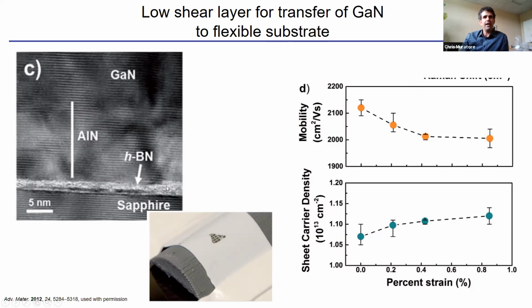And boron nitride has a super low shear strength. It's very easy to tear it apart, just like it has a structure that's a lot like this mica. It's really easy for me to tear a sheet off of the mica, and it's really easy to break this hexagonal boron nitride layer, which is like 3 or 4 or 5 layers. It's easy to split it in two. And so you can grow this GaN device and then tear the material off and attach it to another substrate.